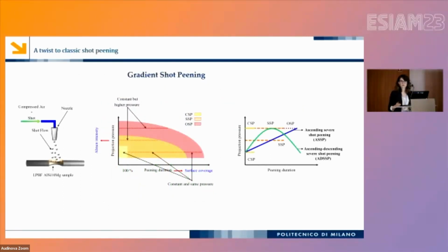Focusing on shot peening, which was the main impact-based treatment that we considered, we tried also to develop a new treatment, which we called gradient shot peening. What we do normally in shot peening is that we fix a pressure that is inducing the kinetic energy that is being transmitted to the material, and then we change the exposure time. With this treatment, we were increasing the as-built samples' roughness. Although the fatigue performance was improved, we always had the issue with the roughness.